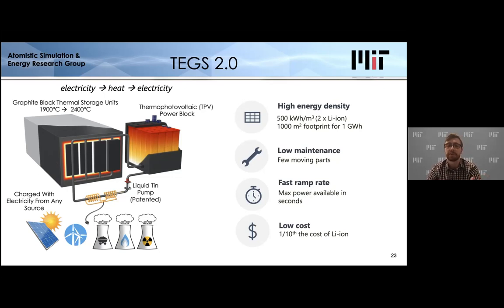So graphite we know works well with tin. Graphite also has a very high specific heat. It's a great material for thermal storage. It's relatively cheap. So basically what we do is we heat the tin with power from the grid. We use that tin to heat these graphite storage blocks. We're still oscillating between the same temperature range, 1900 Celsius and 2400 Celsius. Then on demand, we can pump the tin back through these power blocks, pump it to the thermophotovoltaic power block, and produce power.